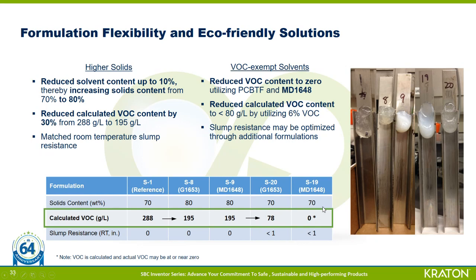So here we have S-19 and S-20. And the picture on the right illustrates the slump samples. And although samples S-19 and S-20 had slightly higher slump, they were less than 1, whereas the other ones measured basically 0.